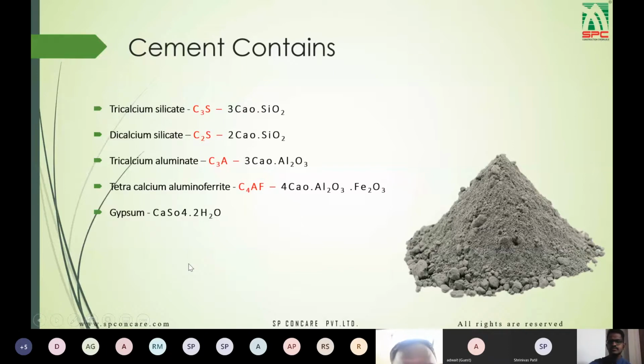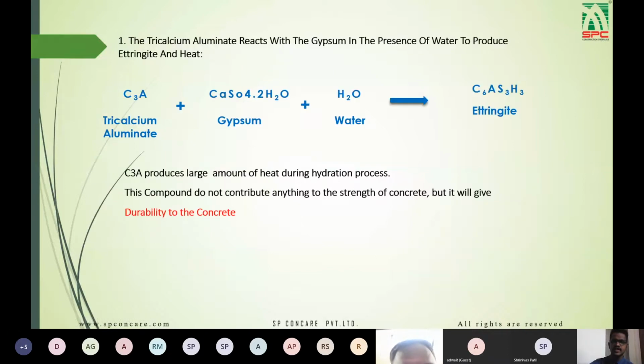So we are going to see the reaction with water. The first reaction is the reaction of tricalcium aluminate with gypsum and water. The tricalcium aluminate reacts with the gypsum in the presence of water to produce ettringite and heat. You can say the C3A, that is tricalcium aluminate, reacts with water and gypsum to form ettringite. This reaction produces a large amount of heat during the hydration process.